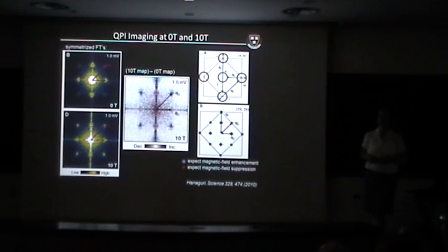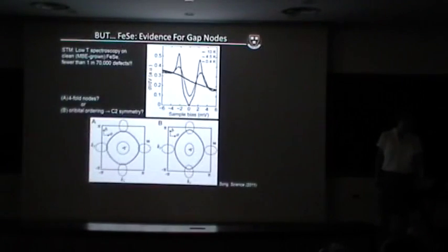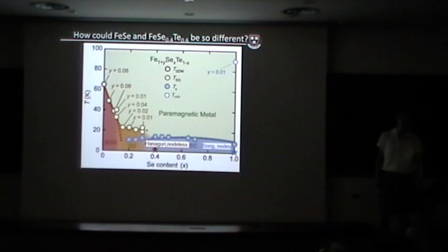However, the reason I was asking this question is that I was at a conference early this week, where people were saying that there were microscopic calculations of precisely that, trying to take into account vortices and multi-band effects, and they saw none of this. They saw no suppression with magnetic field in the calculation. And the argument was that you only see the suppression if your vortex is close to a defect. Essentially, if you have a pinned vortex on a defect or somewhere nearby, then you see this effect numerically.